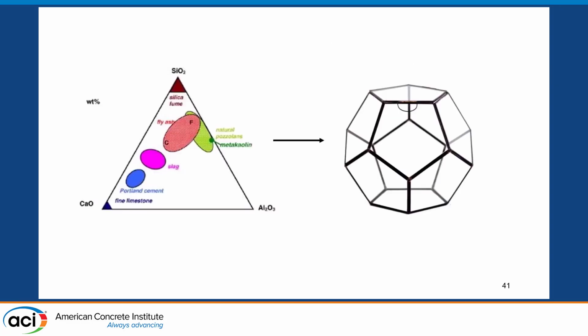But you've maybe seen this ternary diagram before. Maybe if you're a fly ash person, maybe you've seen this plot, maybe you've seen class C versus class F. And this is a diagram that shows how much silicon, how much calcium, how much aluminum, and where different SCMs typically plot. And a lot of people have hypothesized that these are the main oxides that dictate or guide what's going on. We're building like an 11-dimensional figure here and looking at where these things fall and then where certain performances are for different criteria for different performance of that concrete mixture.